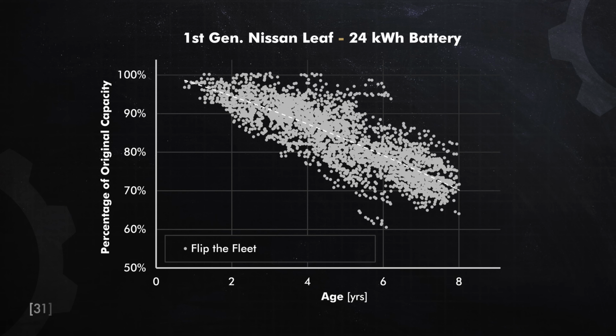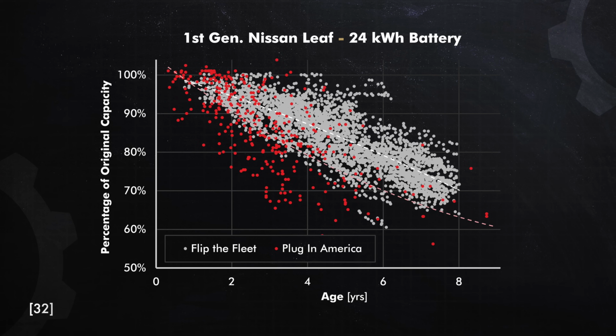The New Zealand EV promotion organization Flip the Fleet has collected over 2,000 battery capacity measurements for the oldest Leafs. On average, this data shows that after 8 years, you can expect battery capacity to be reduced to 70% of its original capacity. Similar data has been collected by Plug in America for more than 360 Leafs. The Plug-in America data is similar to the Flip the Fleet data, although it does show a slightly greater capacity loss for a similar age.